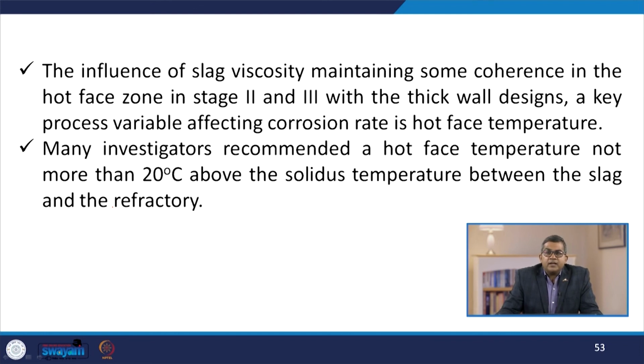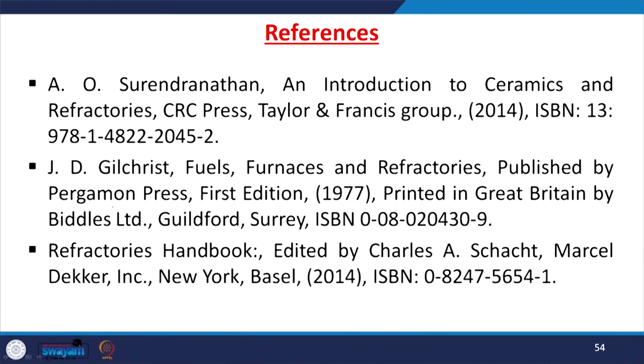With the thick wall design, a key process variable affecting corrosion rate is hot face temperature. Many investigators recommend a hot face temperature not more than 20 degrees Celsius above the solidus temperature between the slag and refractory zone. So, in this lecture, we have discussed various thermodynamic concepts pertaining to refractory operation. Apart from this, we have discussed the corrosion aspect in the refractory, and for your convenience, we have listed several references, which you may utilize for further reading.